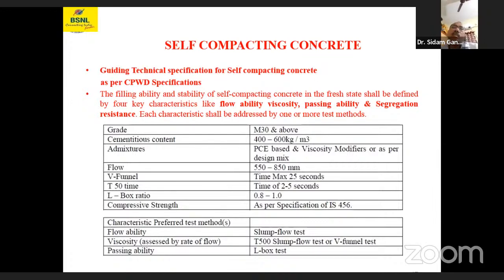If you cast cubes, it requires additional time for getting 90% strength. Generally, we test cubes at 7 days and 28 days, but it requires 2-3 days extra. Suppose we want to test the 7 day cube, we have to test those cubes at 10 days. If we require the target strength at 28 days, it requires 2-3 days extra because the use of this superplasticizer requires more setting time. So these are the properties.